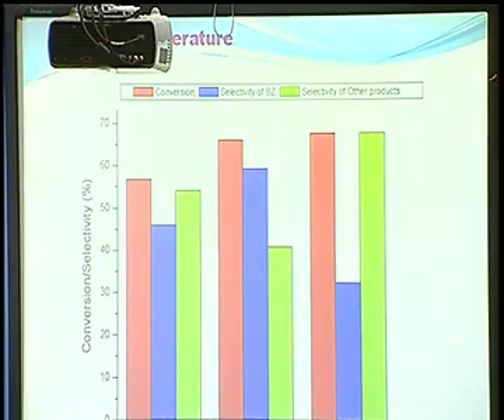Now the effect of temperature, it is clearly indicated that when temperature increases from 70 to 80 degrees centigrade, then conversion increases, but there is no marked change when we increase the temperature to 90 degrees centigrade. Hence 80 degrees centigrade has been taken as optimum.